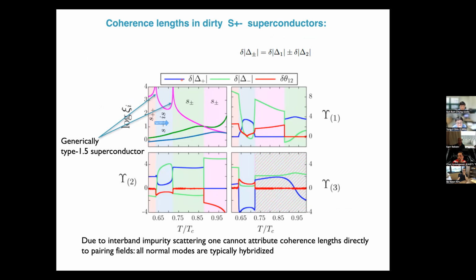This example shows a calculation of normal modes for dirty s plus minus superconductors. These are small deviations in the phase, the sum of the moduli, the difference of the moduli, and the phase difference. And these are what linear combinations of them constitute normal modes. And here you see the linear combination. So the Leggett mode becomes mixed with the relative density mode, even at the level of linear classical theory.